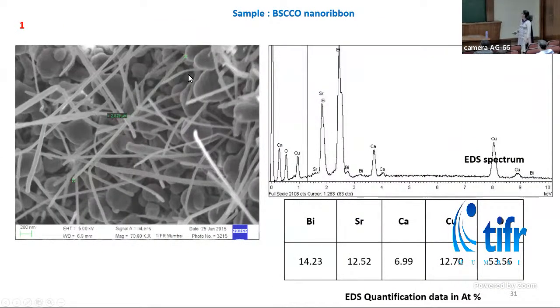Here is an example of BSCCO nanoribbons imaged or detected using this EDS technique. These are nanoribbons which are 50 nanometers in size and 2 microns in length. By BSCCO, I mean bismuth, strontium, calcium, copper oxide. Here the phase of this BSCCO material is very important because its Tc, superconducting transition, depends on which phase it is in. 2212 BSCCO, by 2212 I mean bismuth 2, strontium 2, calcium 1 and copper 2. So 2212 BSCCO will have different Tc than 2223.